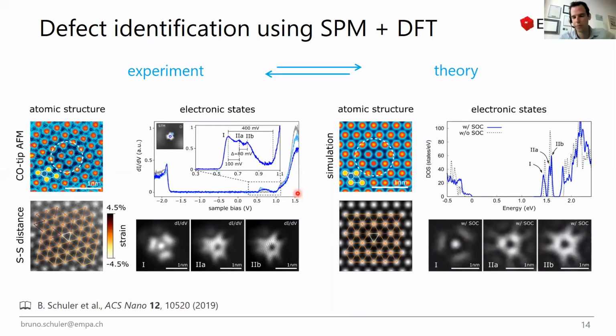But now how do we really come up with these assignments, right? This is really not something which is immediately clear and should be illustrated on this slide on the example of chromium at a tungsten site. So what we essentially do is we record all the data we can with the STM and AFM, do spectroscopy especially. This gives us the kind of fingerprint of these states. So for instance, chromium has 3 states close to the conduction band edge, which are labeled here 1, 2A, and 2B. We can map out how they look in real space. We can record an AFM image to really see that it is a tungsten site defect. And then sometimes we even observe strain, so kind of a local contraction of the sulfur atoms.